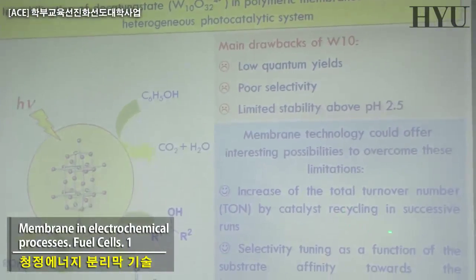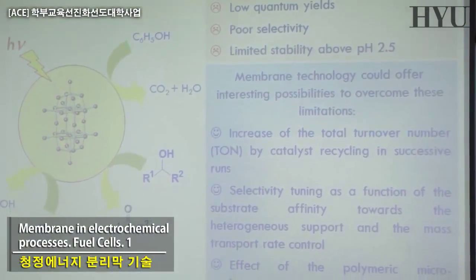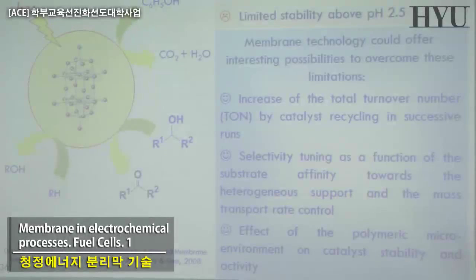We can reuse and reuse this catalyst, because when immobilized, you can just clean or separate it from the reaction volume, so that you can increase the total turnover number by recycling in a certain number of runs. This can be quite a significant number. We can tune, change a little bit, the selectivity as a function of the substrate affinity. As I was mentioning, when you immobilize your catalyst in a certain environment, the function of the polymeric phase, hydrophilic, hydrophobic, supplying electrons or accepting electrons, can significantly change the overall behavior of your catalyst. So that can be done here.